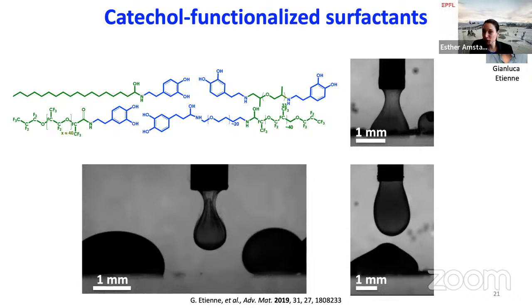One thing that we wanted to do, which also was very much inspired by the really nice work of Laura on the vesicles, is to completely remove the oil, because if we completely remove the oil, we wouldn't have this issue on transportation anymore. This is something that we failed. We never managed to remove all the oil from the shell. We only could remove 95% of this oil.